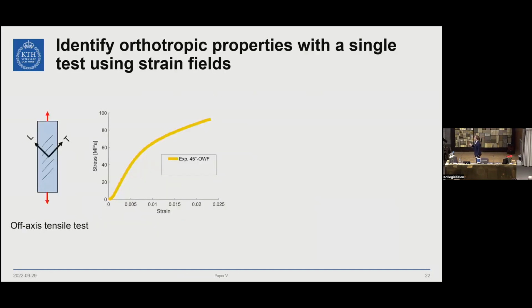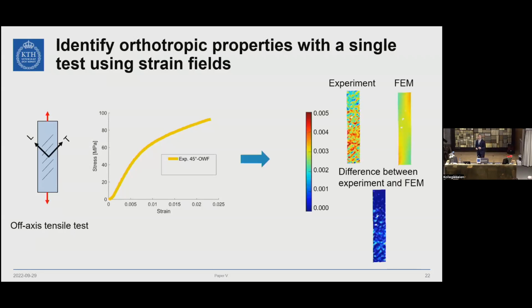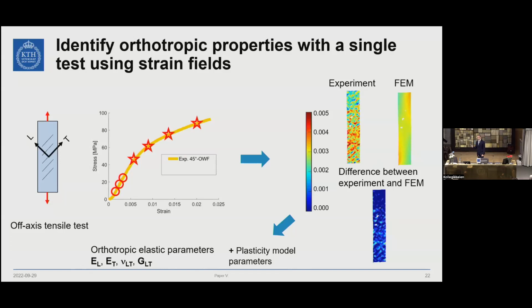And if we do an off-axis tensile test, we can see that there is a linear behavior in the beginning, which translates to a non-linear behavior. We can take the strain field measurements with the camera and investigate how it deforms. We can do the same thing in a finite element model to describe this kind of behavior. And then we take the difference between those 2 strain fields. And from that, we can choose to take strain fields from the elastic part to identify the elastic properties. And then we can do the same thing for the nonlinear part, where we can identify plastic model parameters. And this is done by updating the finite element model until this difference map is minimized.